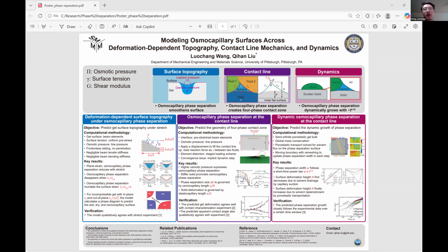When we compress the gel, the solvent can be squeezed out and submerge the surface. And we have a phase diagram here to predict whether the surface is dry or wet under different loading conditions. The same phenomenon was also found in the experiments. And in part two, we focus on wetting at the droplet contact line.